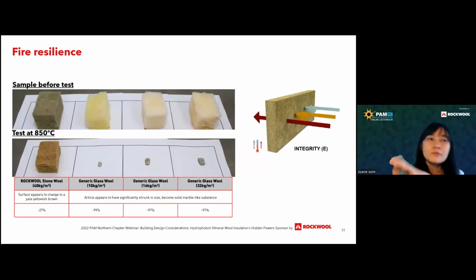Okay, so we look into the comparison here. We subject the Stonewool and Glasswool to a certain very high temperature. This is what we call a sintering test. So you can already see the difference here. A 50 mm sample of Glasswool and Stonewool, 40 kg, and Glasswool 10, 16, and 32.